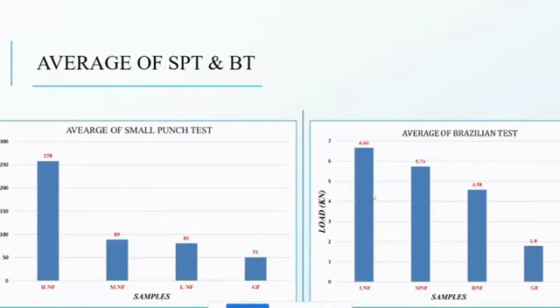For the Brazilian test, since we are doing diametral testing and applying the load horizontally, we can tell that the low fiber gives better results. It is not as it is in the small punch test. Because we apply the load horizontally, more fiber at the contact surface can generate more cracks inside the sample.